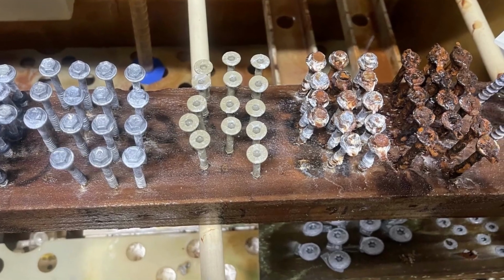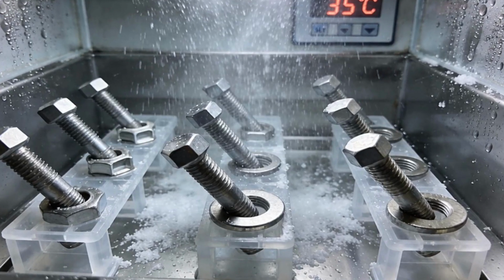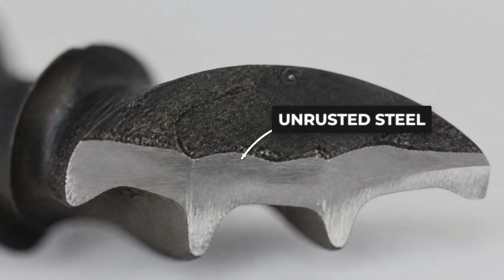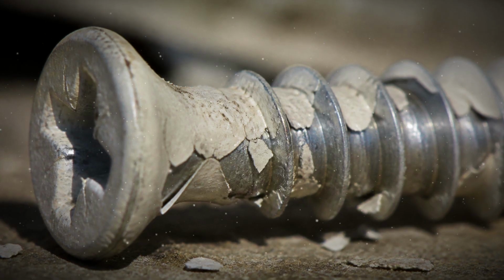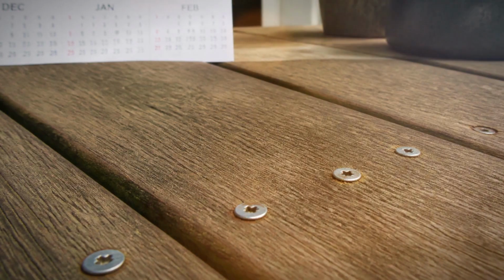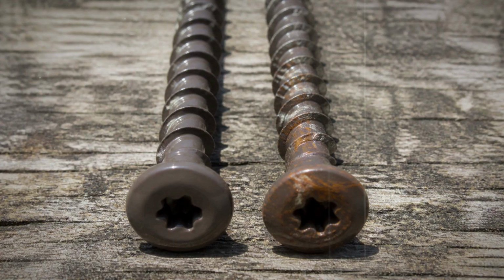In independent acid salt spray testing, premium ceramic-coated brands like GRK and Spax did hold up well, but held up well means the coating showed damage. The steel underneath hadn't rusted yet. The protection was already wearing through. Coated screws stay rust-free for roughly 10 to 15 years, and only if the coating stays intact.